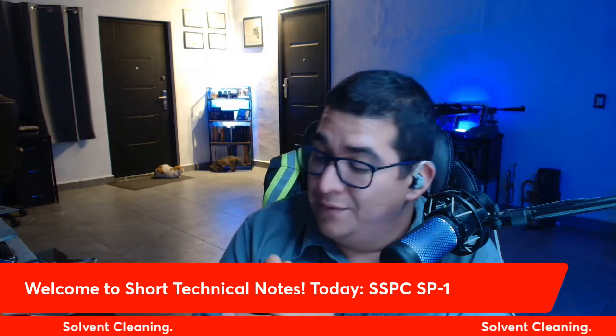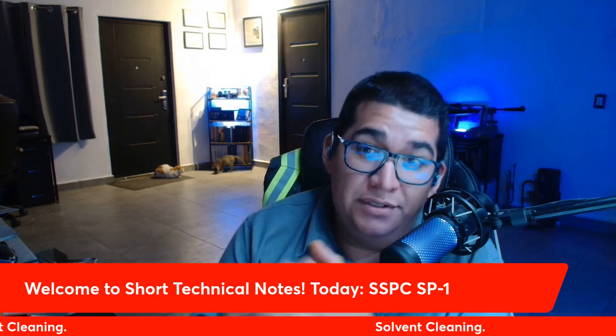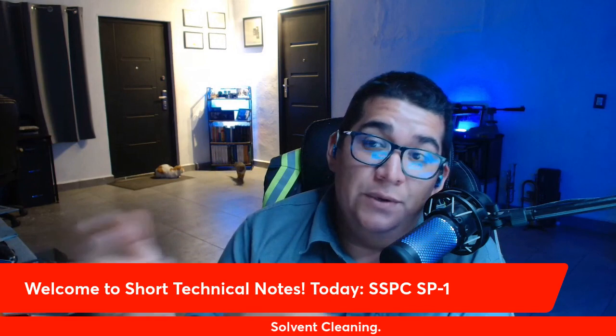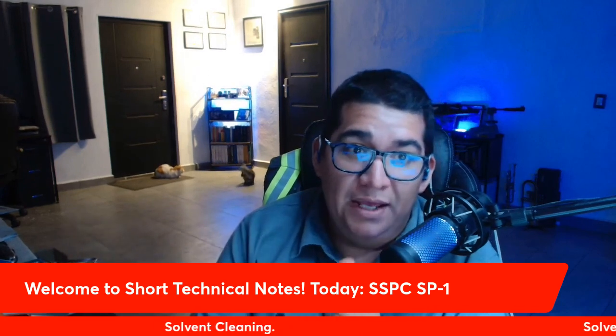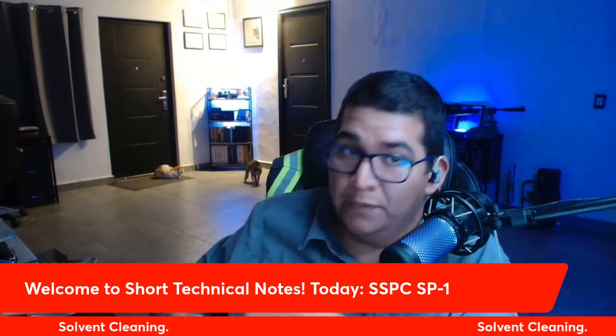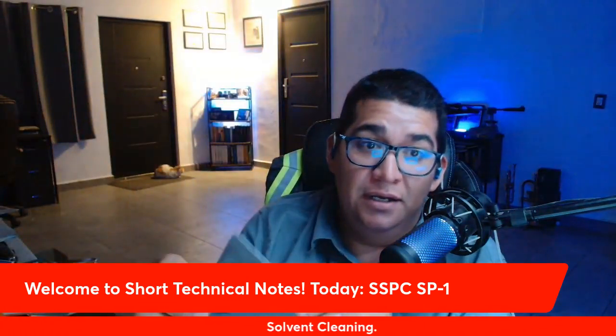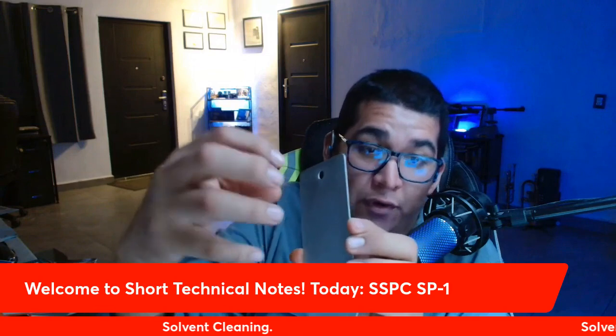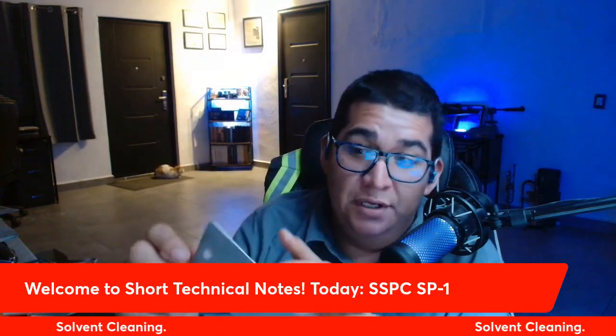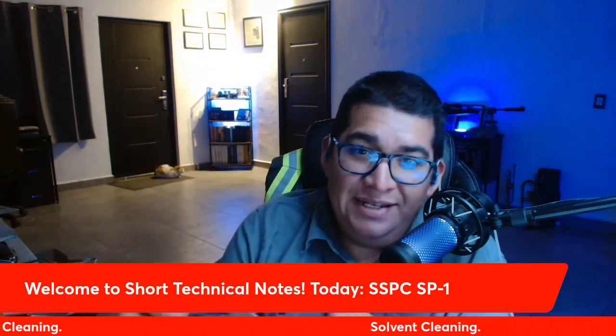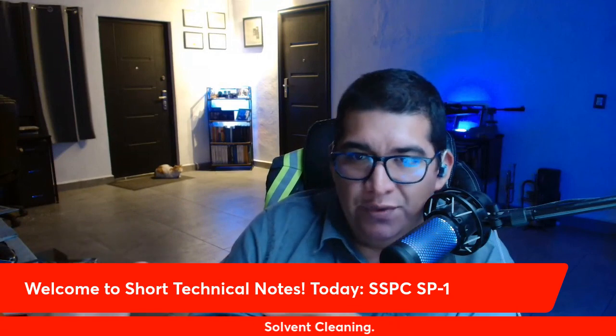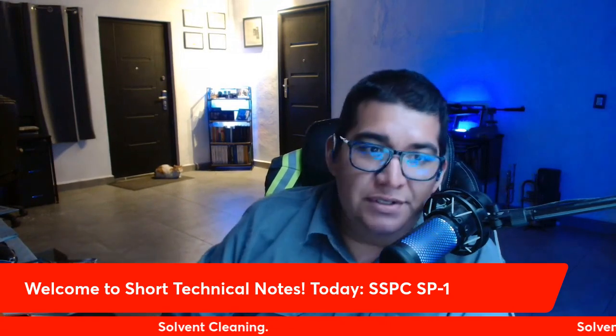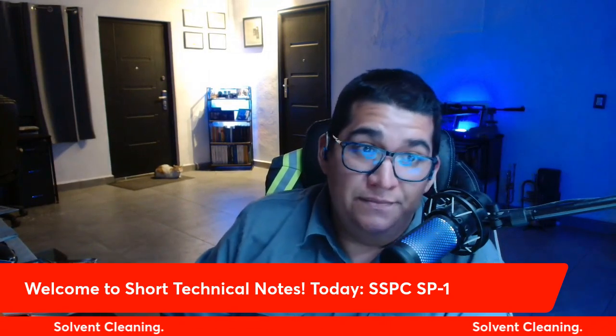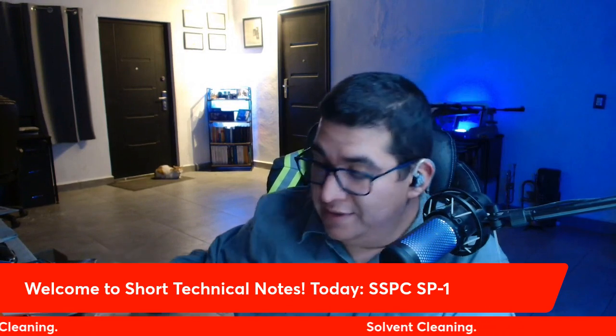We apply clean water onto the surface that we would like to inspect, and we watch for big water drops over the surface, or lenses. Depending on this lens creation, we may know if there is some grease or oil contamination. This is the water break test.